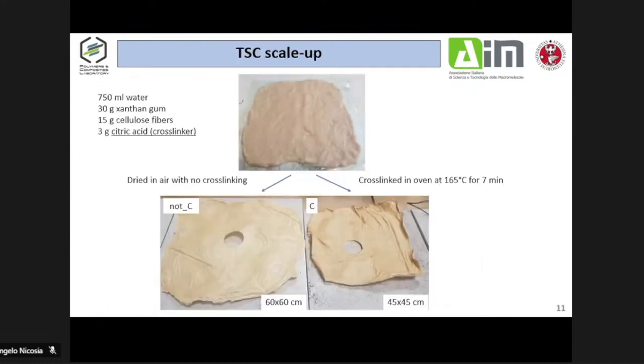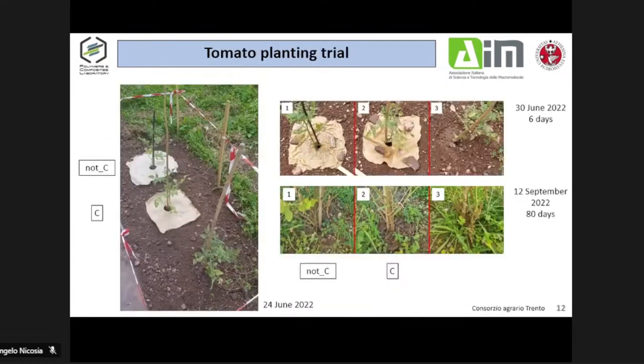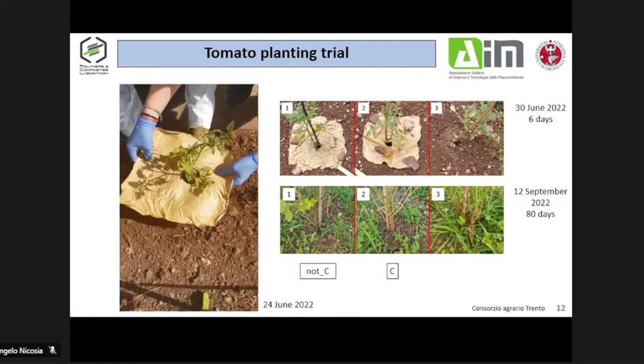About the topsoil cover, we made a scale-up version using citric acid, which is a natural cross-linker. We studied the effect of the thermal treatment of the material. We developed two products, one not cross-linked in oven, and the other cross-linked in oven at 165 degrees C. And we planted tomato plants because they are very easy to cultivate by anyone. It is a sort of accelerated test to assess the feasibility of this material in practical conditions. This is how we install the material at the base of the plant.